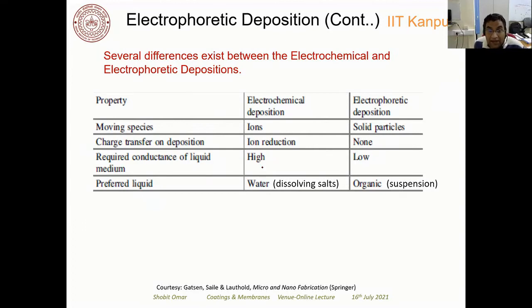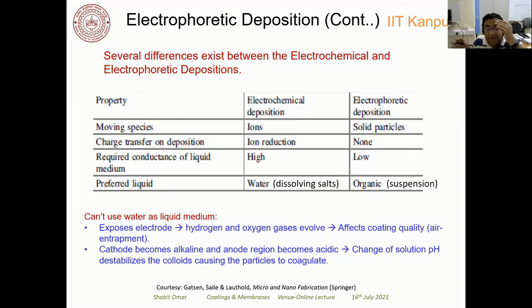The conductivity of the electrolyte in electrochemical deposition should be very high, but here it should be low. You require a dielectric liquid, and normally in electrochemical deposition we use water, right, which has some salts inside. But in electrophoretic deposition we do not want any water. That fluid should not have any water. The reason is that if you have some water, then hydrogen and oxygen gas will evolve on the cathode and anode side, and that will create some porosity in the film. So we do not want any water present in the liquid medium.